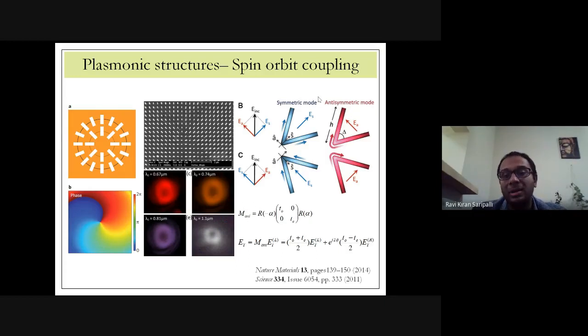So, just for example, if you design such kinds of nanostructures, these are plasmonic structures, and mostly people use gold nanostructures on top of a glass substrate, and using lithographic techniques you can fabricate these kinds of structures. Different polarizations of the input beam act differently on such structures. So if you come in with a polarization in this ES direction, your plasmon resonances will be in the direction shown by the blue arrow. But when you come in with a polarization in the EA direction, or the antisymmetric mode, your plasmon resonance acts differently.